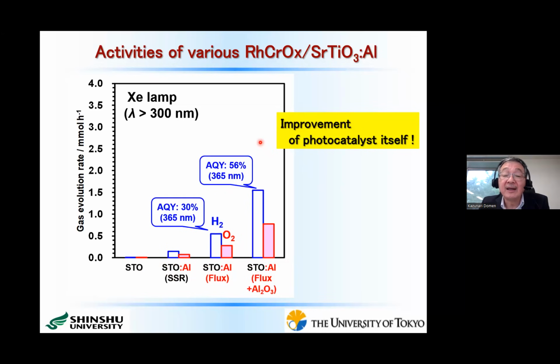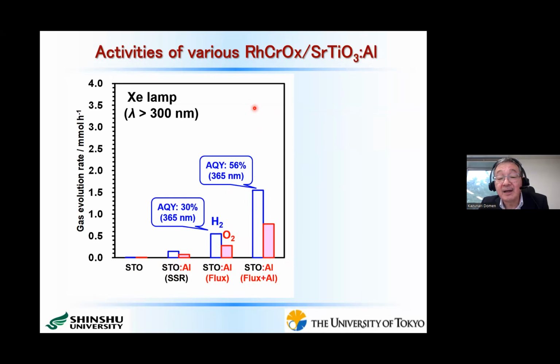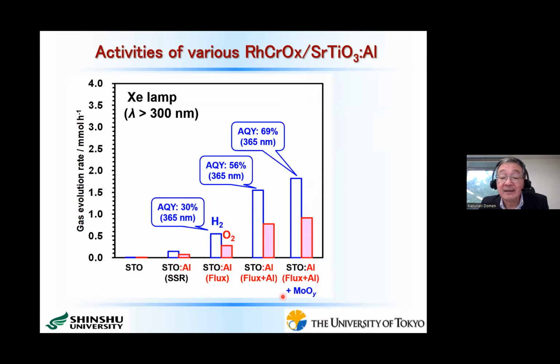Then we modify our co-catalyst. I mean that we add the oxygen evolution co-catalyst. At first, we found that when we added molybdenum oxide as an oxygen evolution co-catalyst, the loading amount was only 0.1 weight%, very small amount. But as you see here, the apparent quantum yield was very close, almost 70%. And this is a very good quantum yield for overall water splitting reaction.